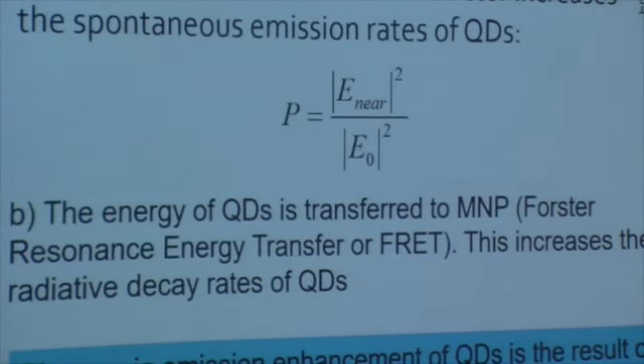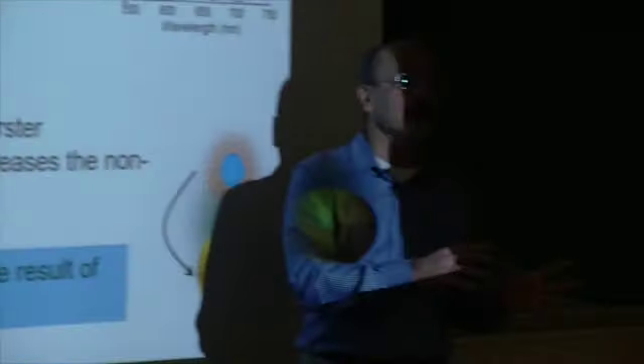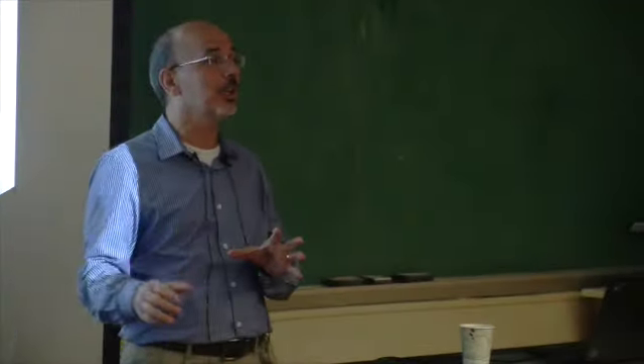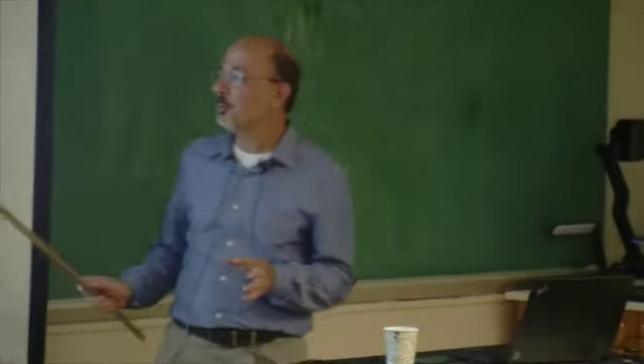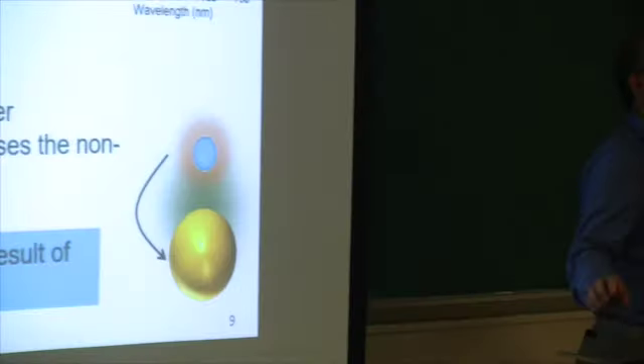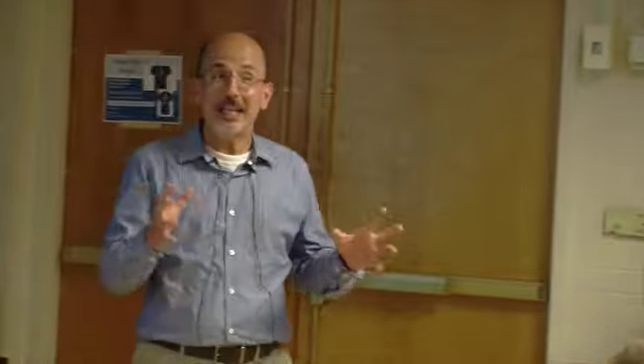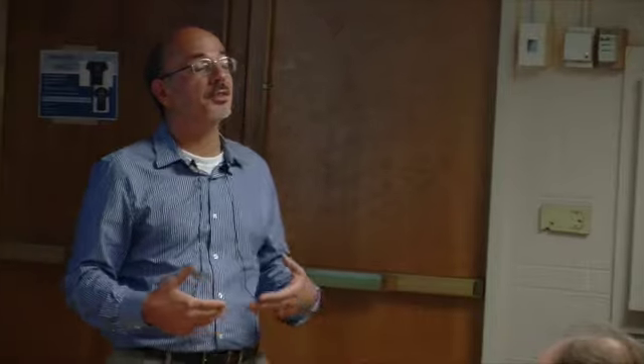But the other one, which is kind of playing negative, but happens very naturally, is the fact that if you put a quantum dot close to a metallic nanoparticle, while the quantum dot enjoys the intense field of the metal, I'm afraid it actually gives up some of its energy to the metal. And that happens through FRET, or Forster Resonance Energy Transfer, which is common.